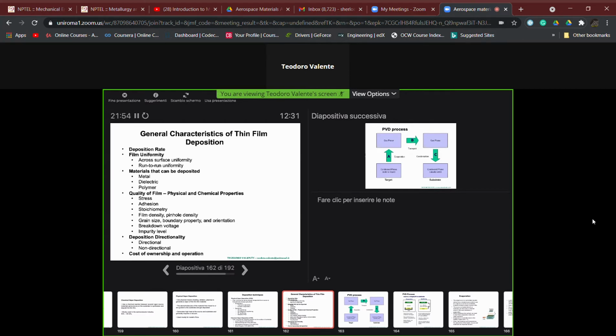If, for example, we are going to fabricate multi-layered coatings, the materials which can be deposited in general can be metallic materials, metallic alloys, but also dielectric materials as well as polymer materials. And the quality of the film is evaluated by physical and chemical properties of the film itself. And so we do have, as we have seen, techniques which are able at lab scale to allow us to make our characterization testing in order to evaluate residual stress where present, the adhesion, the stoichiometry, that is the composition of the film, density, and eventually the defects density, the grain size, the orientation of the grains.